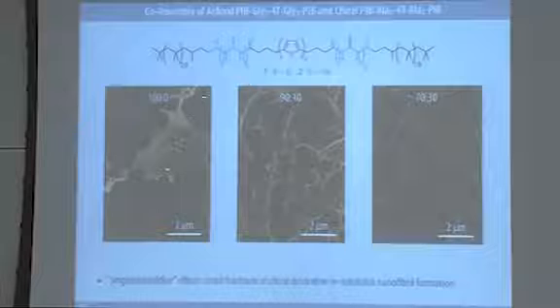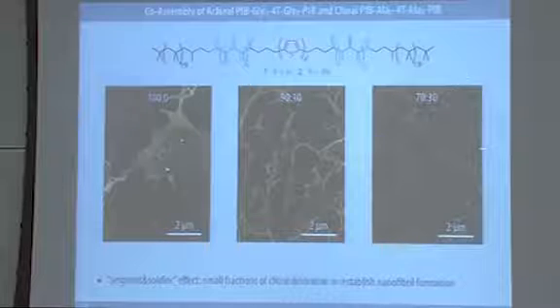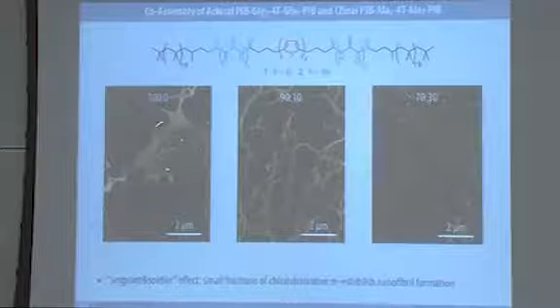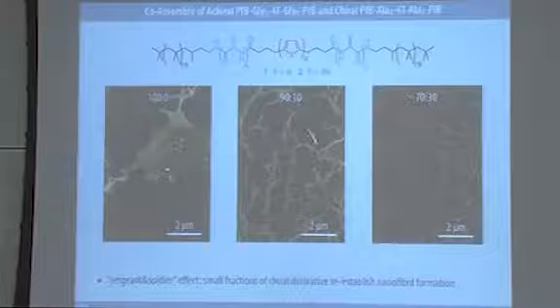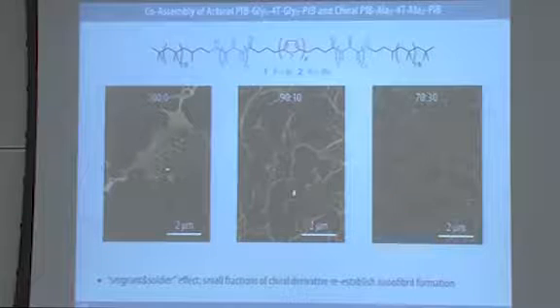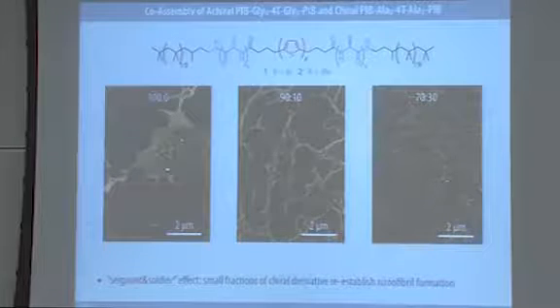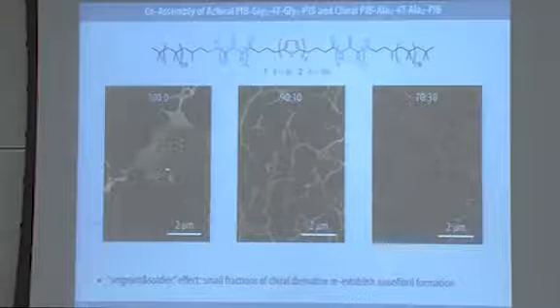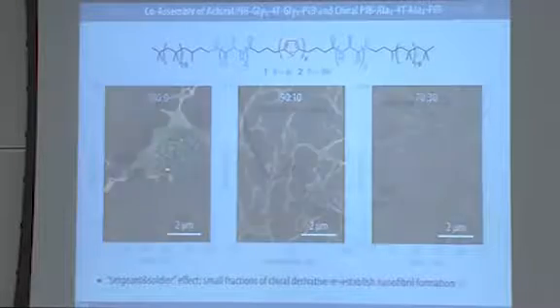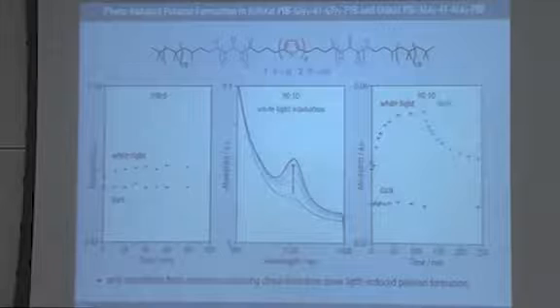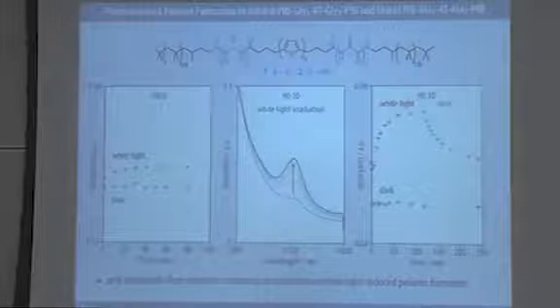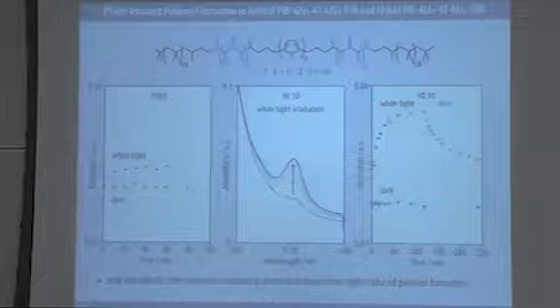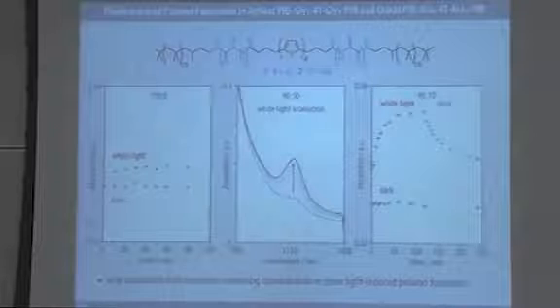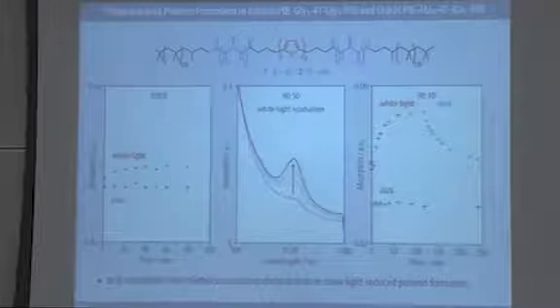So as we add 10% or 30% of the chiral molecule to the system, we go from these monolayer-like films to undefined fibrils to actually pretty surprisingly well-defined fibrils. But what struck us is that if we leave away the chiral component entirely, we do not observe any formation of the radical cations. So there is a topological effect that we do not understand very well in play here.